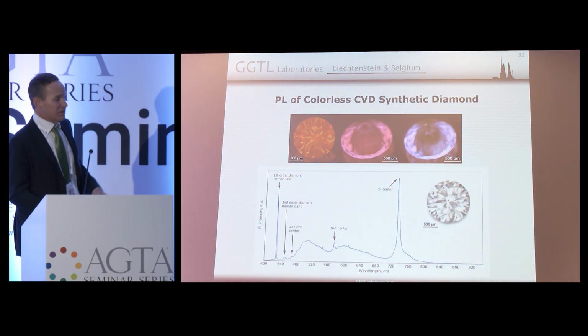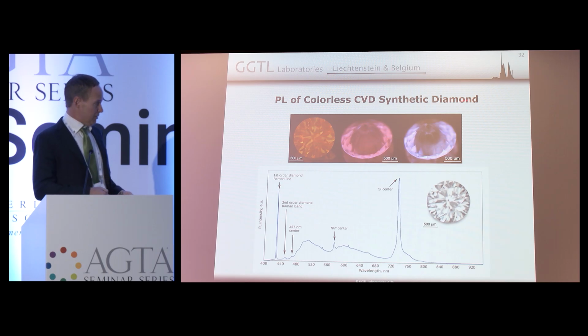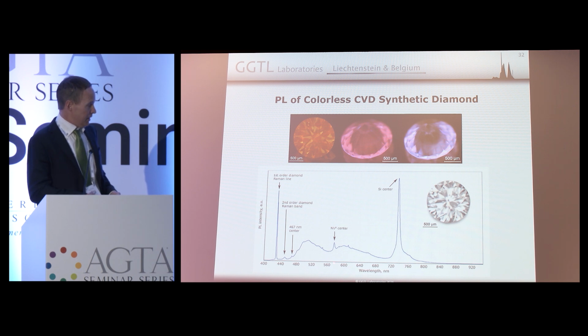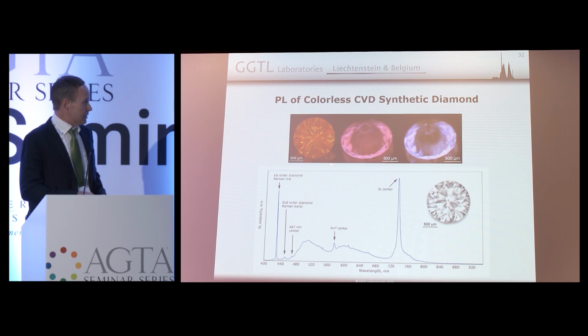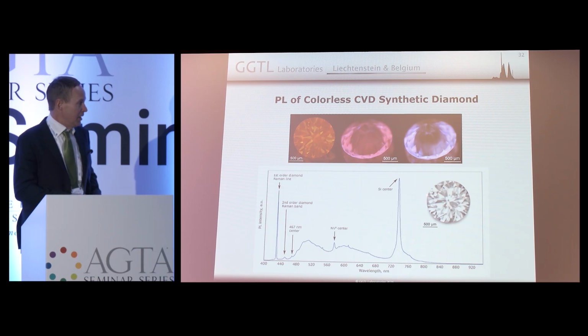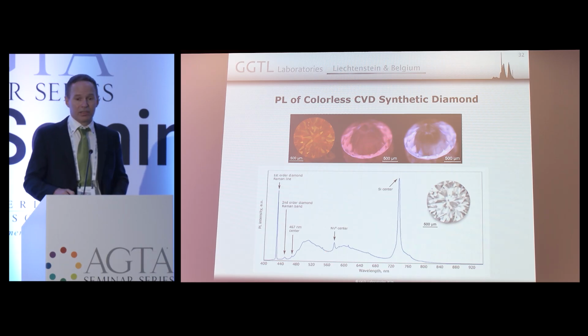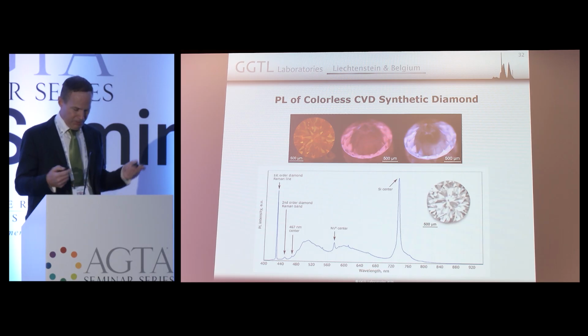The luminescence from an as-grown stone, as I mentioned before: the red fluorescence is from the NV center. So here in the orange to red domain, the NV0 center causes the fluorescence that you see here. And the yellow fluorescence that we saw before is from the 467 center. So this combination is very typical, and the silicon center here is very typical as well. If you have a spectrometer on hand, even small spectrometers will visualize that in most CVDs.